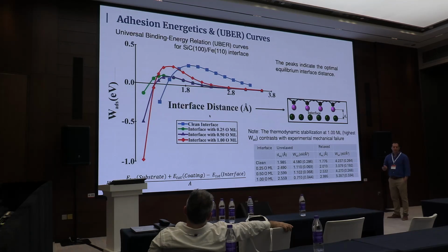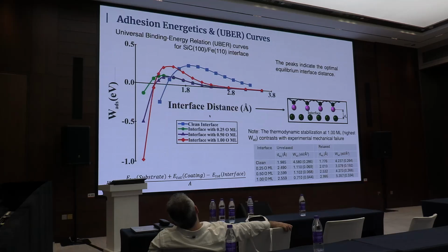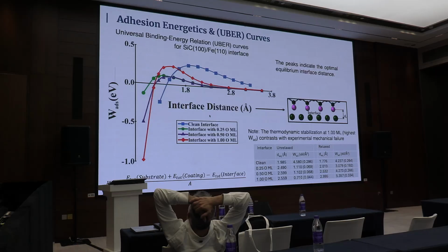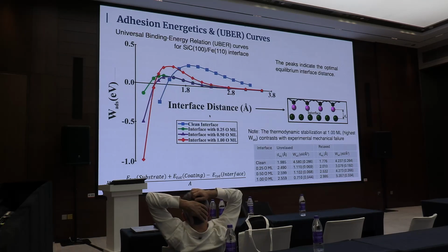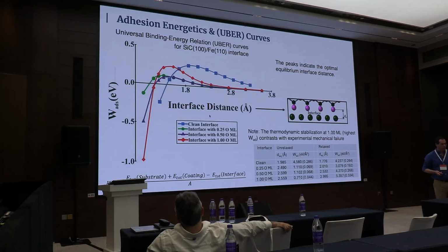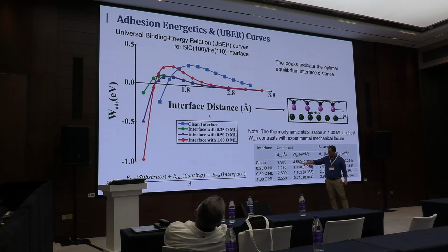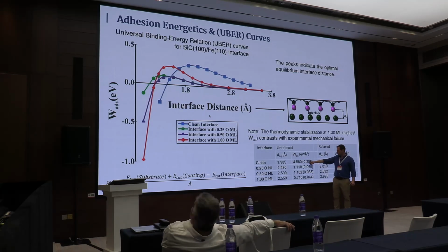So for the system with the arrangement before we relaxed it, do you remember the first slide where we put all of the oxygens well arranged? We don't relax the system, we don't make the atoms move to look for the lowest energy. We can compute just one cycle. We call this a self-consistent computation, and we compute how much the energy is at this point. So this is the first column here. If the system doesn't relax, and I pull the surfaces apart, I will find that the maximum value the system will resist for not having oxygen is this amount.